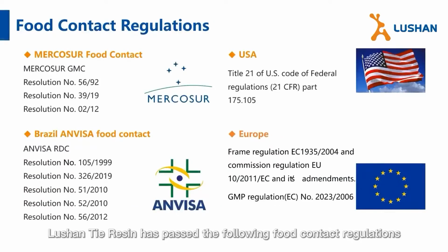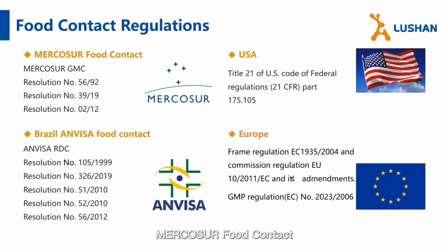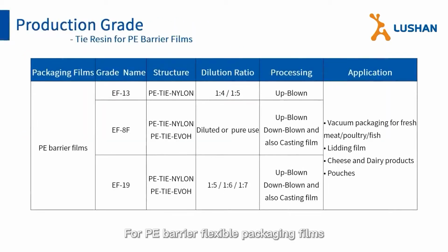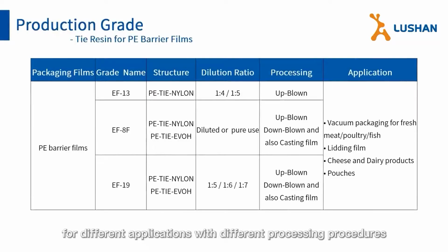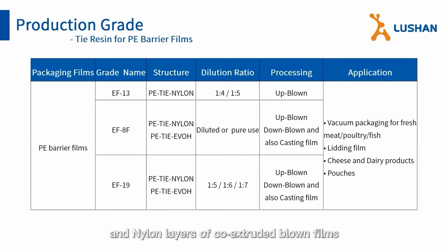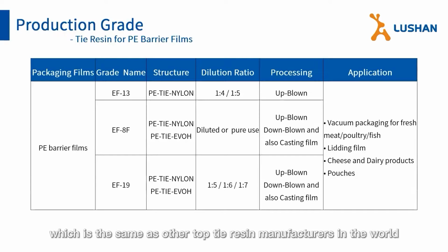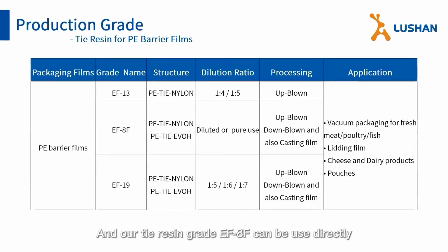LUSHAN Tie resin has passed the following food contact regulations: Mercosur Food Contact, Brazil Anvisa Food Contact, and the regulations in USA and Europe. For PE barrier flexible packaging films, we have developed many grades of tie resin for different applications with different processing procedures. For example, our tie resin grade EF13 is developed for bonding PE and nylon layers of co-extruded blown films, and grade EF19 offers super strong adhesion to PE and EVOH layers of co-extruded blown and cast films. The adhesion strength could be 9 to 10 N/cm, which is the same as other top tie resin manufacturers in the world. And our tie resin grade EF8F can be used directly without any crystallizing point shown in the films.